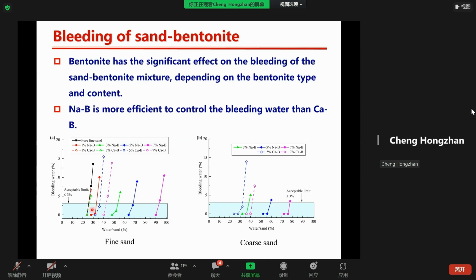And it was expected that the bleeding water for both sands was increased by increasing the water to sand ratio. We can also find that the bentonite has a significant effect on bleeding of the sand bentonite mixture, depending on the bentonite content and the bentonite type. Moreover, it's clear that the sodium bentonite is more effective to control the bleeding water than the calcium bentonite. So we can conclude that the sodium bentonite is better than calcium bentonite in the condition of workability in the first stage.